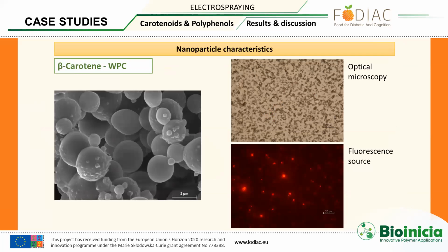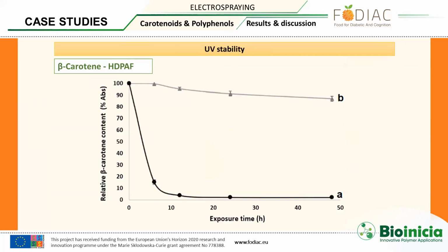We have encapsulated beta-carotene in whey protein concentrate, obtaining spherical microparticles. And we have studied the UV stability of the free beta-carotene, which is the black line, and the capsules, which are the gray line. As you can see, after 10 hours the beta-carotene completely degrades, while our capsules remained stable for a long period.